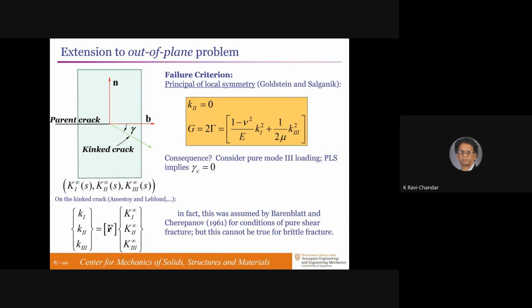Now, the question that is yet to be answered satisfactorily is what's the extension of the principle of local symmetry for 3D problems, that the crack will find the path along which there's maximum tension or minimum shear. People have interpreted this as saying K2 equal to 0. Local mode 2 is 0, but nothing about mode 3, local mode 3. But the mode 3 contributes to energy release calculation. So the same criterion, mode 2 stress intensity is 0. The remaining energy release rate must be equal to the fracture toughness of the material, and that should give you the criterion for the angle gamma.